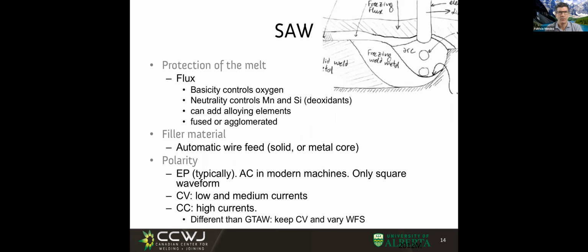Now there is another type of flux in which the powders are made out of agglomerations of other powders, including, for example, metallic alloying elements. And these are called agglomerated. Fused fluxes, because they are essentially crushed glass, tend to have very low moisture. With agglomerated fluxes, we have to be careful to make sure that they don't absorb too much moisture. It could evaporate and create problems of hydrogen when the moisture decomposes into hydrogen and oxygen in the arc.